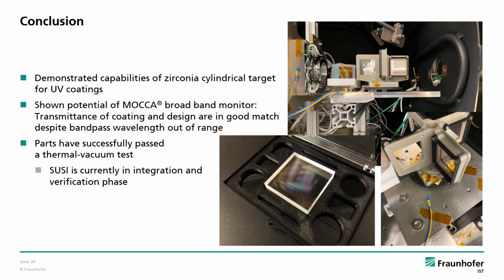With this, I come to the conclusion of my talk. We demonstrated the capabilities of zirconia cylindrical sputtering targets. They are a cheaper alternative to hafnium sputtering targets for the UV spectral range. We could show very good optical properties, down to 300 nanometer wavelengths. Also, we could show the potential of the MOCCA broadband monitoring system. The transmittance of the coating and of the design were in very good match, despite the bandpass wavelength being out of the range of the system itself.